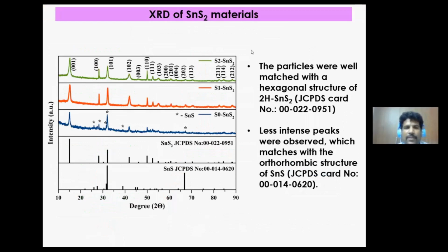After synthesis, first we wanted to know the structure of the material, and with XRD we can predict the nature of the material. So we have done XRD for all three different materials synthesized using different solvent combinations. First, S0, SnS2, is taken for measurement, and we found two different structures, SnS and SnS2. SnS belongs to a P-type semiconductor and SnS2 is an N-type semiconductor. So a mixed formation has arisen. That was confirmed with JCPDS data, given in this figure.